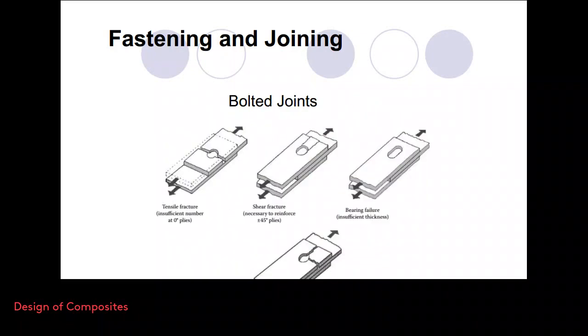So let's look at the failure types of the bolted joints. In fact, here we see a double lap joint, bolted joint. So you may see a failure in the center laminate. This is a tensile fracture. Basically, the number of plies in the direction of the load is not sufficient. This is what it means, simply.